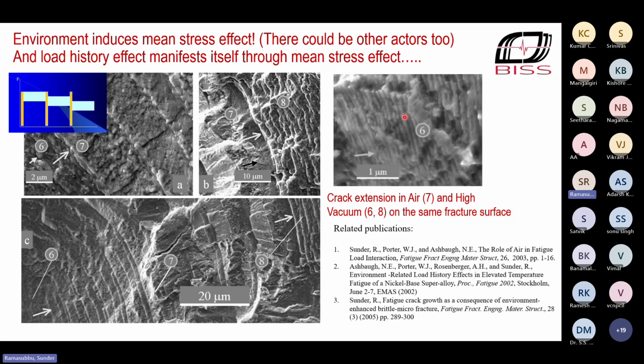So it turned out we made a discovery. And that is that the mean stress effect, one of the main reasons for the mean stress effect is actually the environment. And if you come to think of it, isn't it logical? After all, when the atomic spacing is closer to each other, it's not going to allow diffusion.